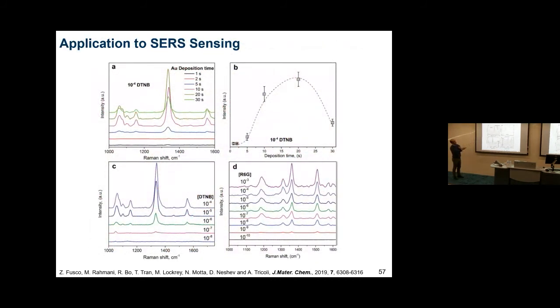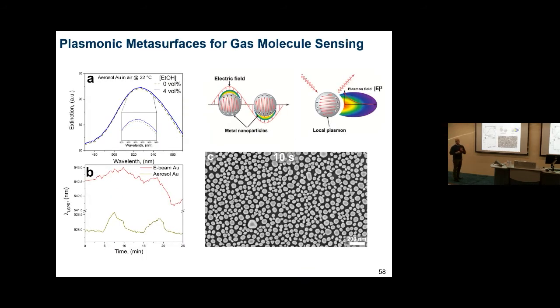We can see that we get the strongest response to a standard analyte, nothing too fancy. It's not one of the best, but it's not too bad either, considering you deposit these things in 20 seconds very rapidly. There is a problem when you try to detect gases with this kind of plasmonic nanoparticle: mostly they rely on the change of the electric environment around them, and gases change the electric environment only a little bit.